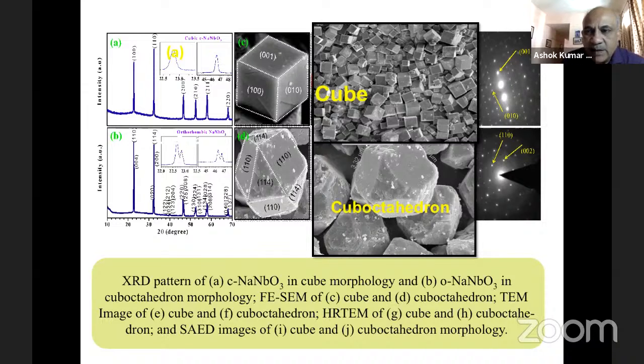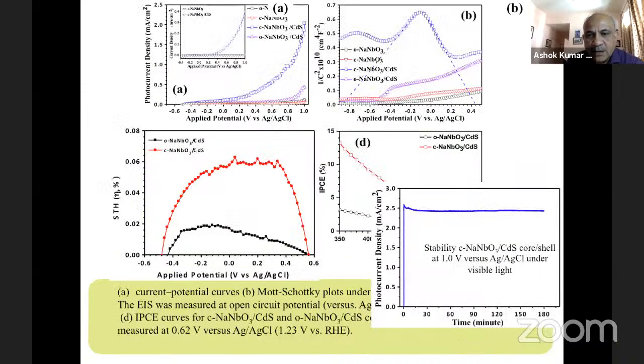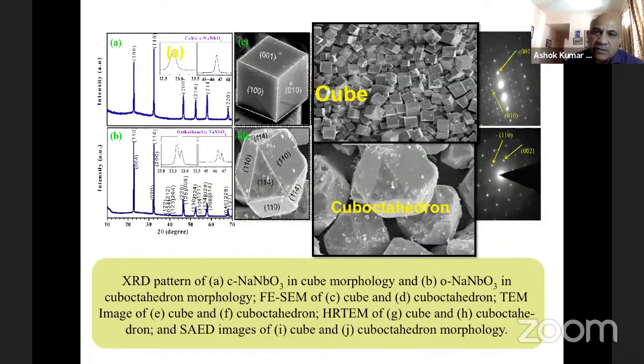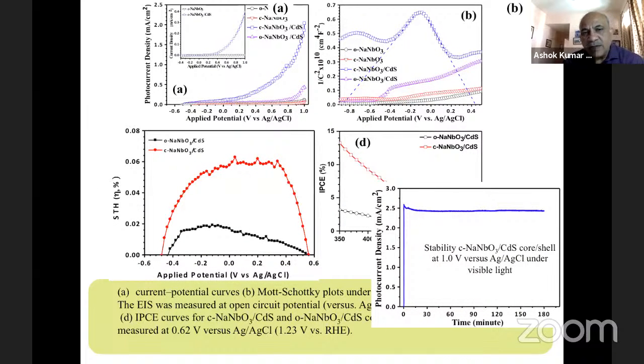So you see these two types of facets will have slightly different surface energies. And so there will be a difference in where the electron and hole should migrate, because there are two options available here. Whereas here, all the energies are the same. So the electron and hole do not have any option. Okay. So when you make the core shell, we make this particle, sodium niobate, in the core. And on top, now you put cadmium sulfide as a shell. So you prepare the core shell structure, and then you do the measurements.